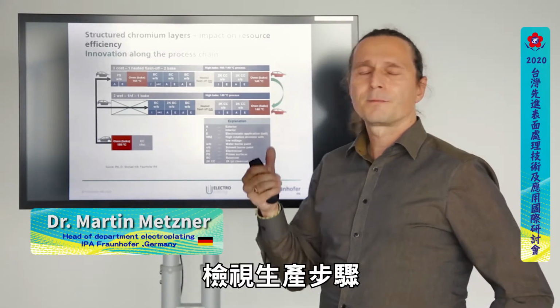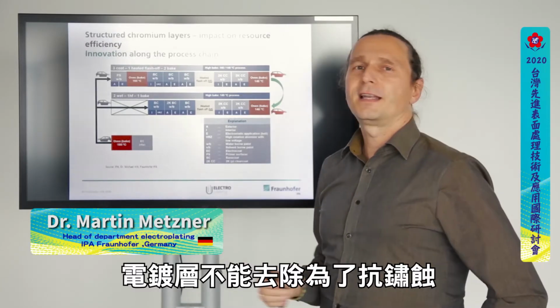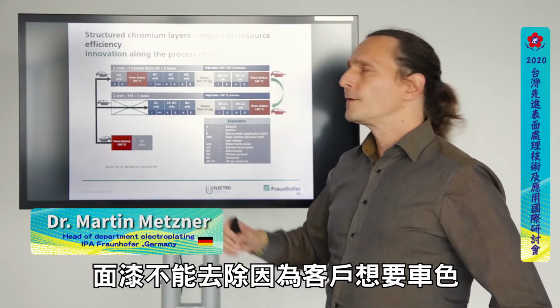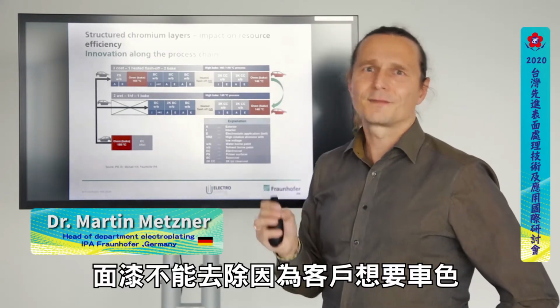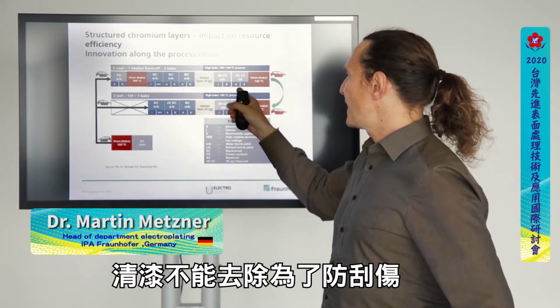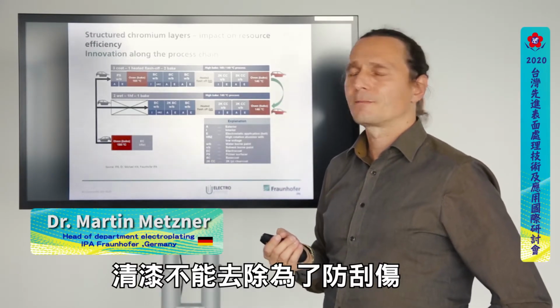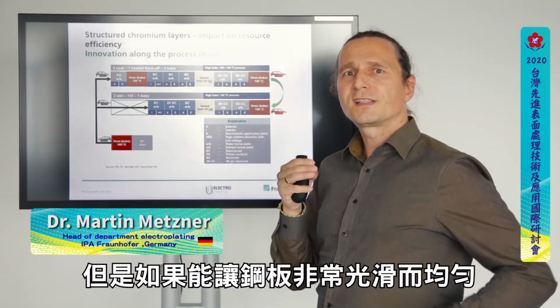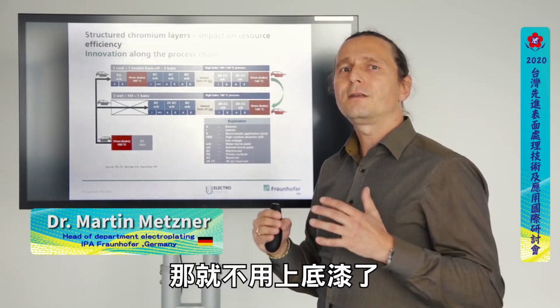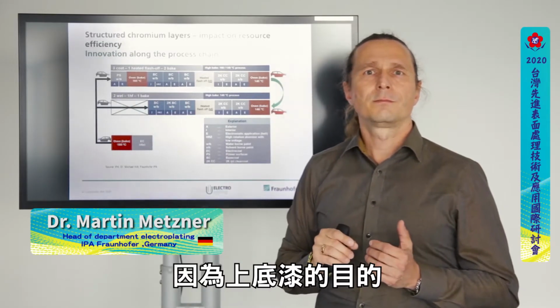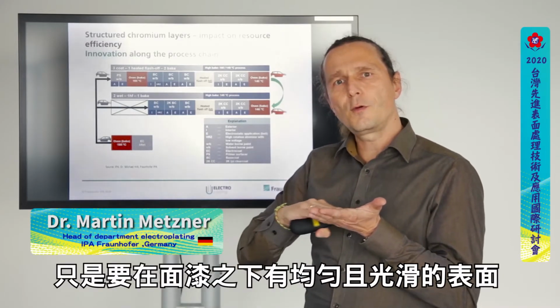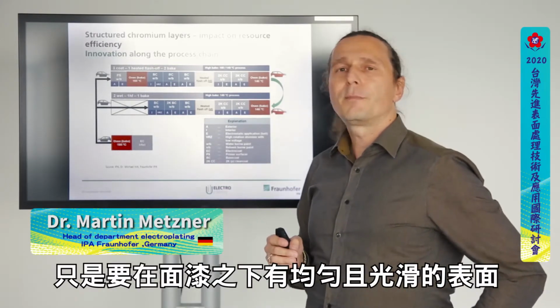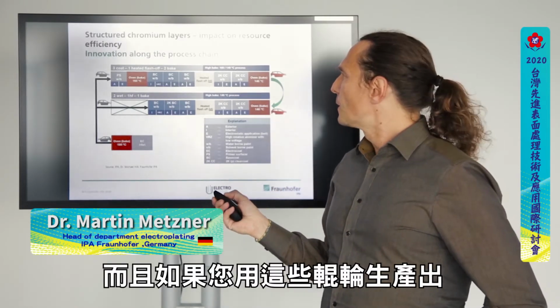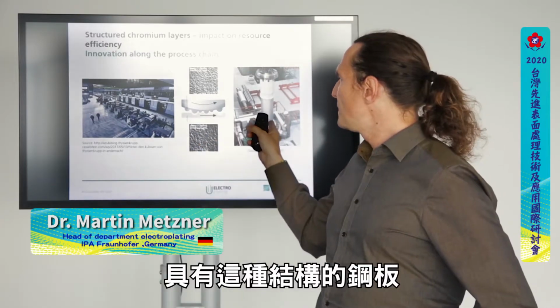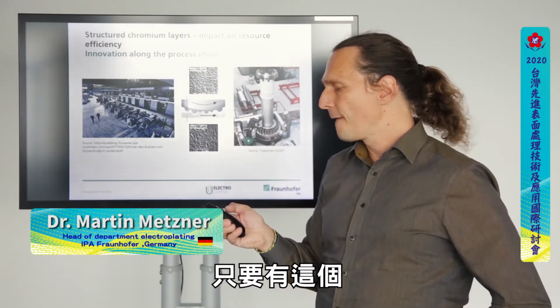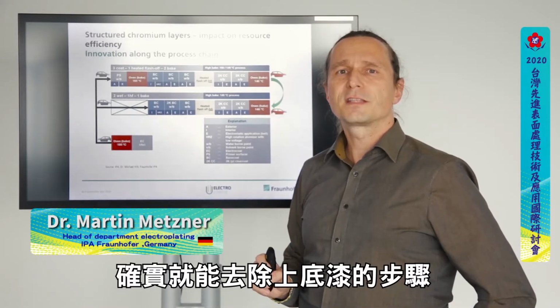When you look at the production steps, you cannot get rid of the electrocoat, because this is for the corrosion resistance. You cannot get rid of the base coat, because this gives the color that the customer wants. And you cannot get rid of the clear coat, because this gives the scratch resistance. But when you have a very smooth and homogeneous steel sheet, then you can get rid of the primer, because the primer is only there to make a smooth and homogeneous layer underneath the base coat. And what is possible when you have steel sheet produced with these rolls, with this structure on it, is really that you can get rid of the primer section.